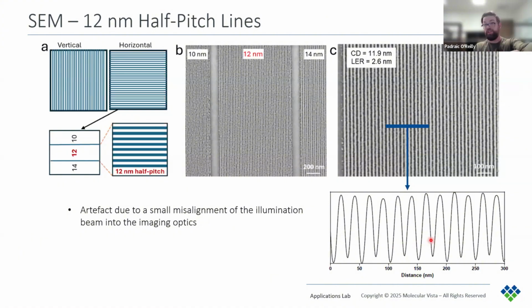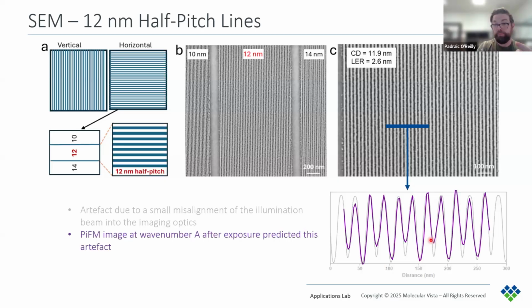So this artifact was actually just a small misalignment of the illumination beam into the imaging optics, which led to every other line receiving slightly more dose than its neighbor. So the upshot of this is that it unintentionally highlighted PiFM's capability to predict the final pattern, including these unwanted artifacts. And you can see this as we overlay the wave number A profile from the exposed sample, so this purple line, on top of the developed SEM profile. So every second dip is shallower.